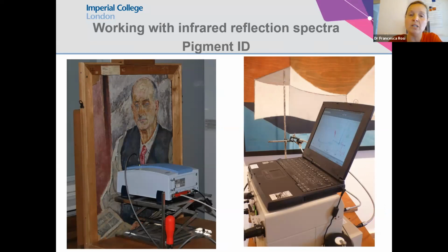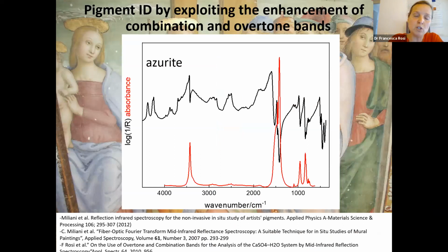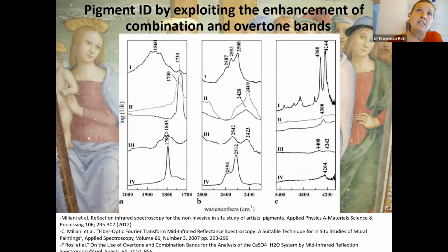Let's start, for example, with pigment identification. As I showed you before, this is the comparison of a spectrum recorded from azurite in transmission and in reflection mode. The fingerprint region is characterized by distorted bands due to the strong contribution of the surface reflection. But you see also the appearance of new bands, which are combination and overtone bands that are not distorted, and they become diagnostic for the identification of materials, for example for distinguishing the different types of carbonate-based pigment. Here you have combination and overtone bands of azurite and lead white, as cerussite and hydrocerussite, as well as malachite and calcite, as we saw before.